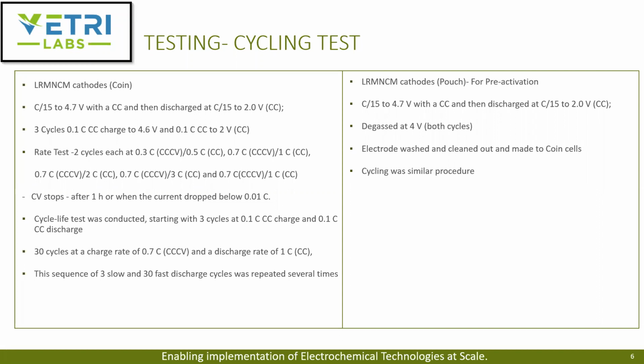So they do rate tests where they charge and discharge at different rates, going almost down to 3C, from half a C to 1C to 2C to 3C, and drop it back down. Subsequently, they also change the charging rate from 0.3C to 0.7C in the process.